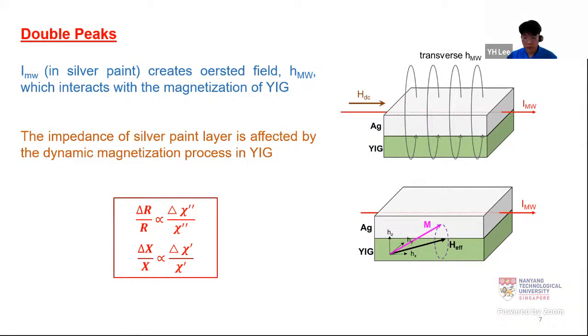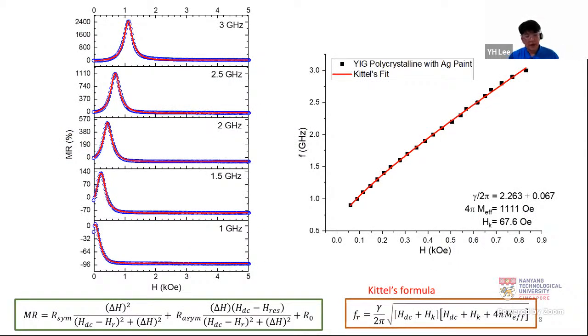The impedance that we measure from the experiment is affected by the dynamic magnetization process of YIG, namely MR, which is directly related to chi double prime, and MX, which is directly related to chi single prime. We recognize that the R and X resemble the absorption and dispersion curves, proportional to chi double prime, the out of phase, and chi single prime, the in phase, respectively. So we fit the MR graph with Lorentzian fitting functions, which account for both the symmetrical absorption and the asymmetrical, dispersive nature.